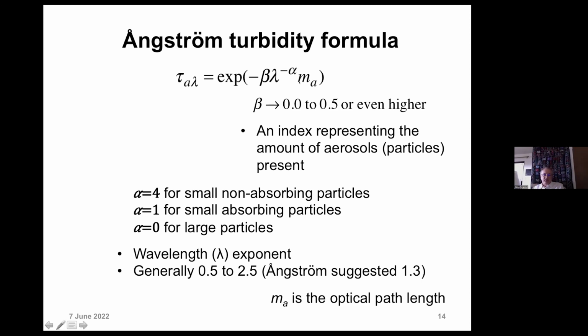And that's what is used to determine for the atmosphere itself when it has particles in it, the parameter m, the optical path length, and the scattering of the atmosphere, which is beta times m. So depending upon the size of the particles, I told you that that's important. Alpha equals one for small, alpha equals four for non-absorbing particles, alpha tends to zero for very large particles. So the exponent of the wavelength is alpha. That describes the change over wavelength. Angstrom himself suggested that this term would be something like 1.3.